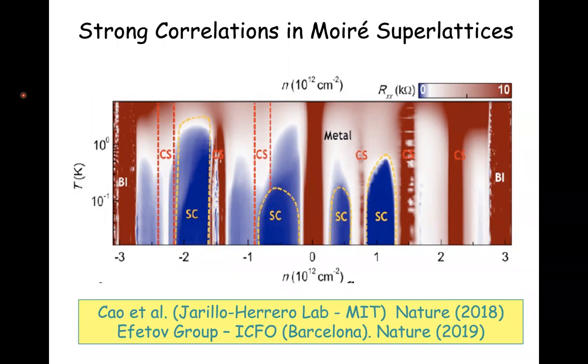And so a typical set of experimental data like this one Pablo would have talked about shows carrier density. This is in these periodic structures I'll talk about. This is changing the number of electrons per atom by 1, 2, 3, 4, down to -4 electrons per atom. And over that range, you see insulating states, superconducting states, and we're learning lots more about these states, and that'll be the main subject of my talk.